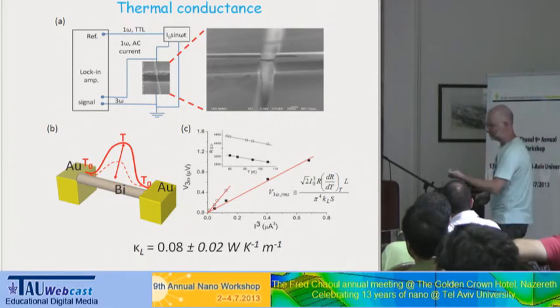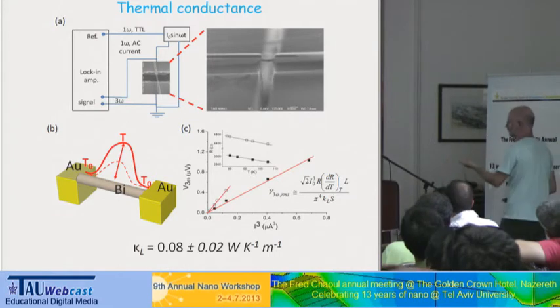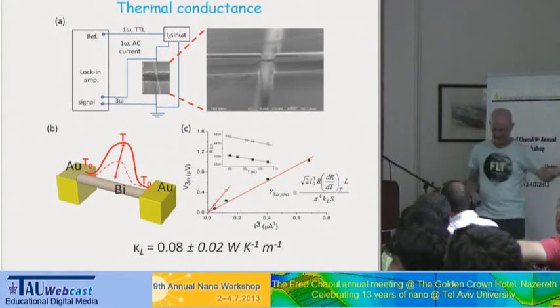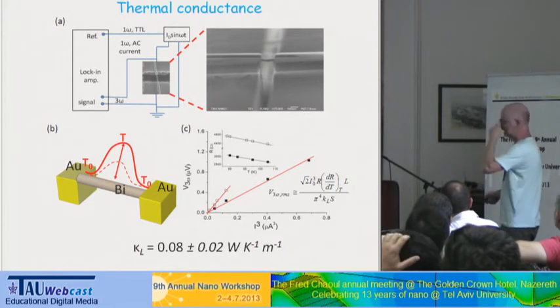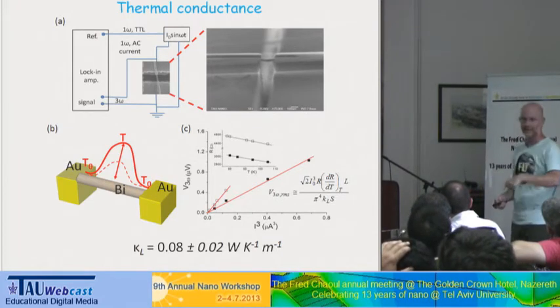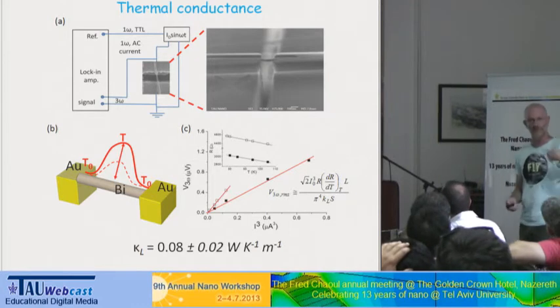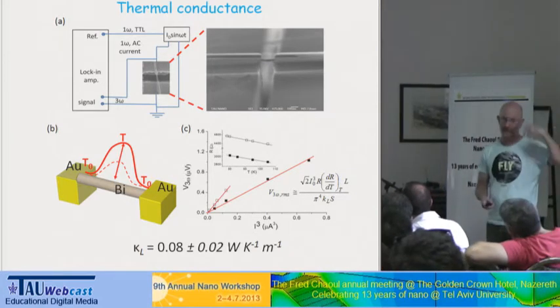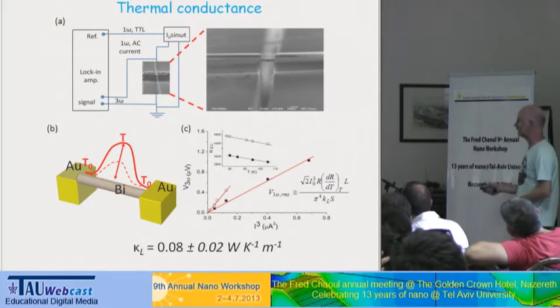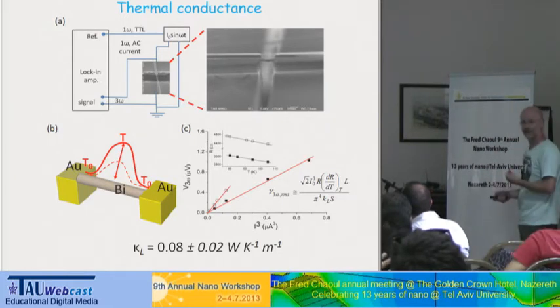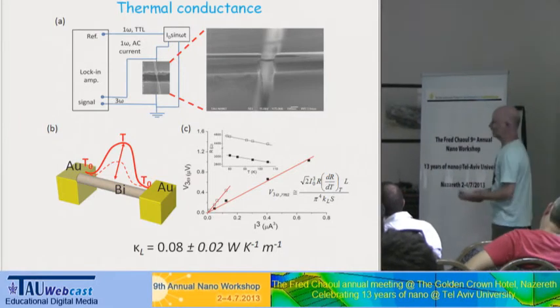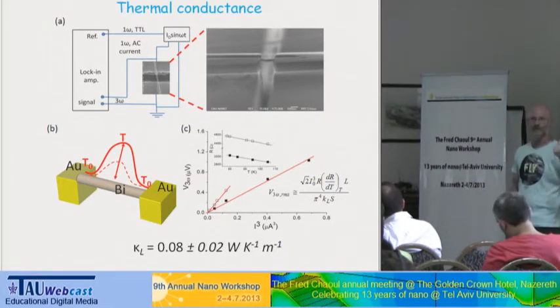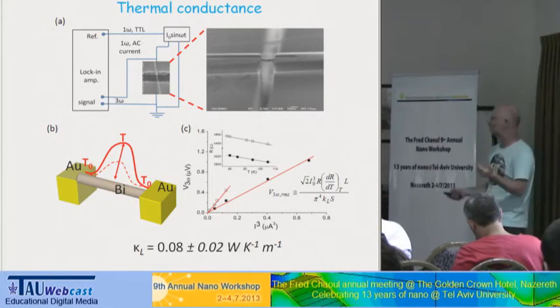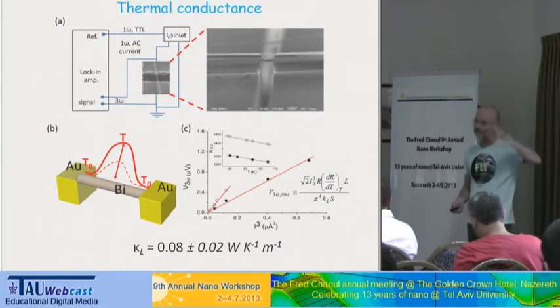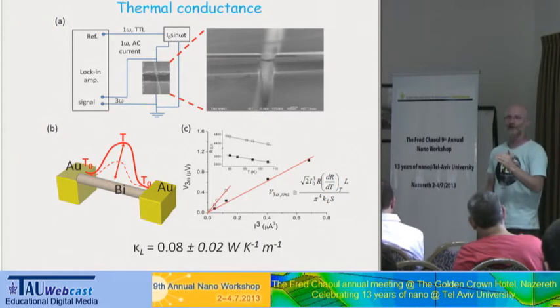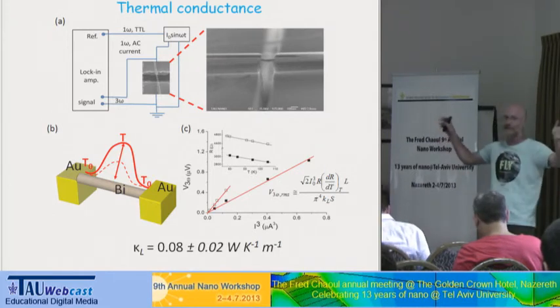Now if you have an AC current going through the wire at a certain frequency, let's say omega, the temperature is going to fluctuate at 2 omega, because the power that you put on the wire is I squared. If the temperature is fluctuating at 2 omega, it means that the resistance of the wire is going to fluctuate at 2 omega. Now, you have current flowing in at omega and resistance fluctuating at 2 omega. It means that you have a voltage component, IR, that is oscillating at 3 omega. And this 3 omega signal is free from any other contribution that you can think of that is happening here.